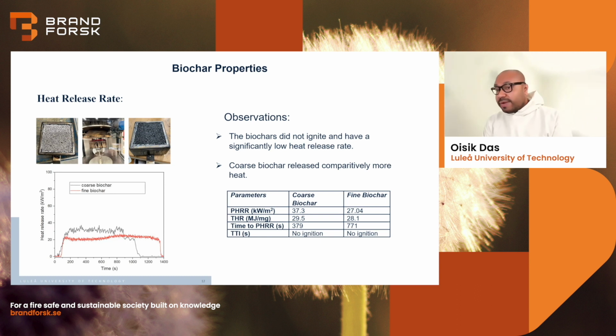The total heat release, that is the area under the heat release rate curve, is also quite low. Here, for both the biochars, we see it's about 30 megajoule per meter square. For most plastics, it's like over 100. The time to peak heat release rate is also quite low, and time to ignition, obviously, it did not ignite, so there was no ignition.